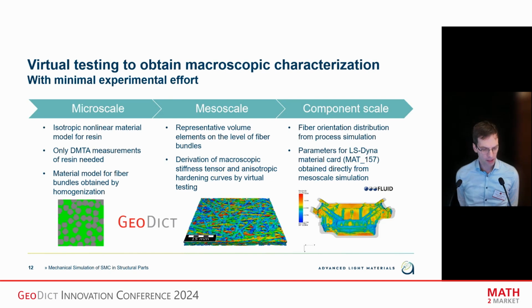This material model of the fiber bundles can then be used in mesoscale simulations, where the fiber bundles are the resolved objects as before. We generate representative volume elements, perform virtual tests on this mesoscale, and from these virtual tests we derive macroscopic stiffness tensors and anisotropic hardening curves, exactly the data we need as input for an LS-Dyna material card. And this material card then can be used directly without any additional parameters. It gets all the data needed from the mesoscale simulation and can be directly used in LS-Dyna for simulations on the component scale.